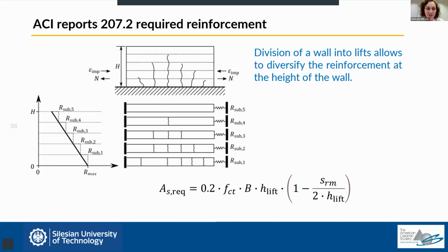But if we do it this way, with such an approach, and we apply uniform reinforcement, it means that the higher we get in the wall, the more over-calculation we achieve. In the American approach, it is explicitly stated that the wall should actually be divided into parts which are called lifts. And we can differentiate the amount of reinforcement needed at each height, because as you can see, we are producing not just one model, but multiple models of partially restrained ties. And in each of these ties, we calculate the crack spacing, which depends on the degree of restraint which is present at this level of the wall. So this can really give us a lot of